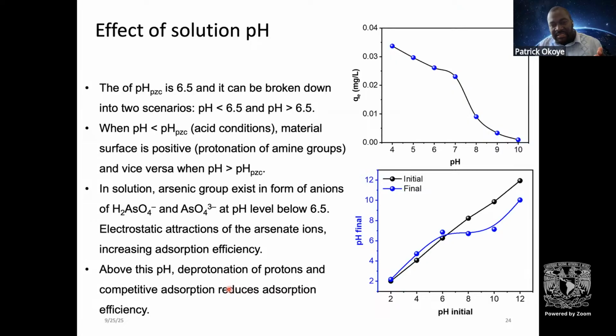When we used only carbon, we found out that from our point of zero charge, which is near 6.5, we were not able to remove a lot of arsenic, because arsenic in water also has negative ions. They deprotonate and form arsenate ions or arsenite ions. So we tried our best to have a highly positive surface to be able to remove the negative species. Remember, like charges repel and unlike ones attract.